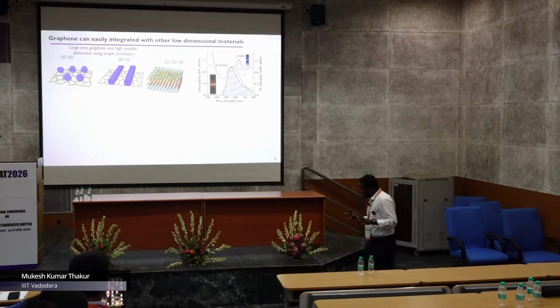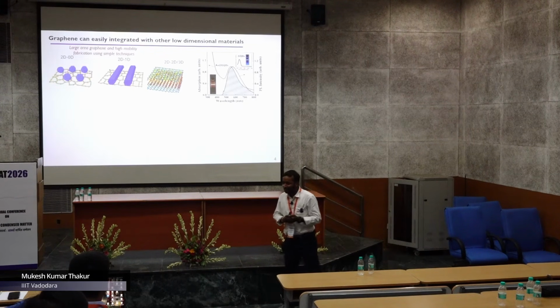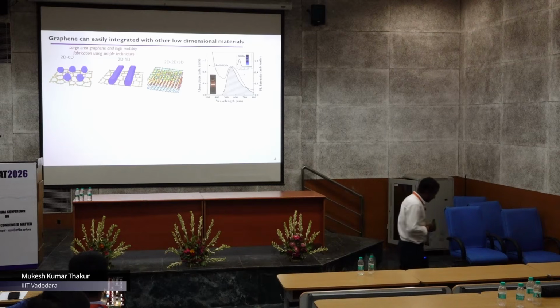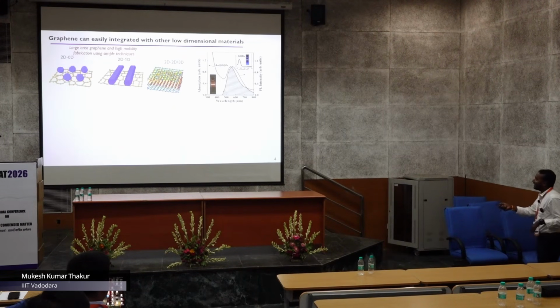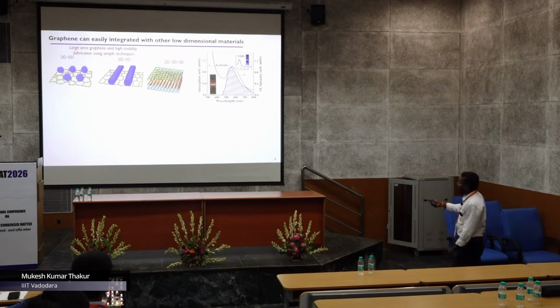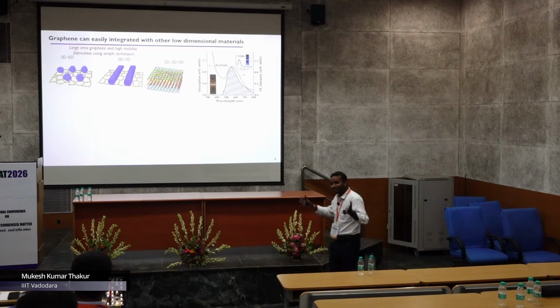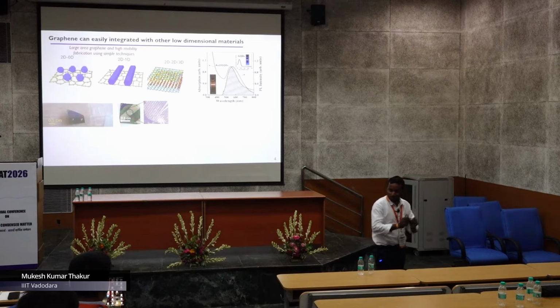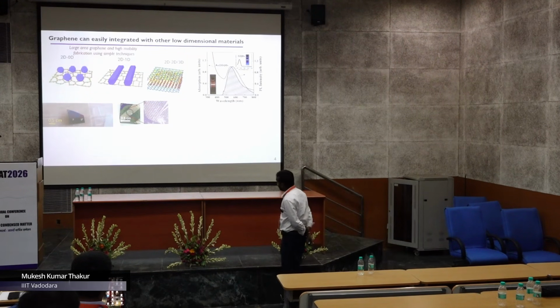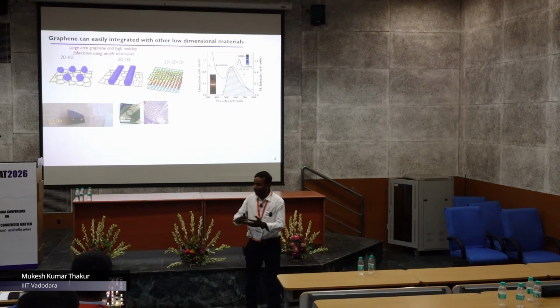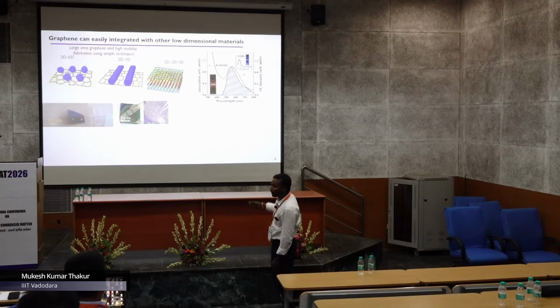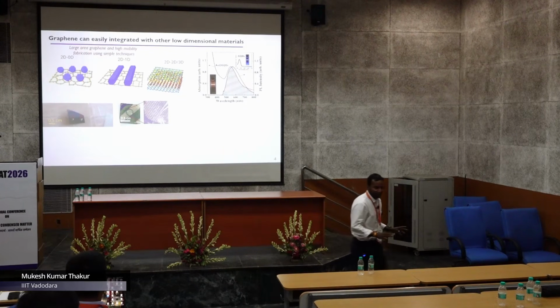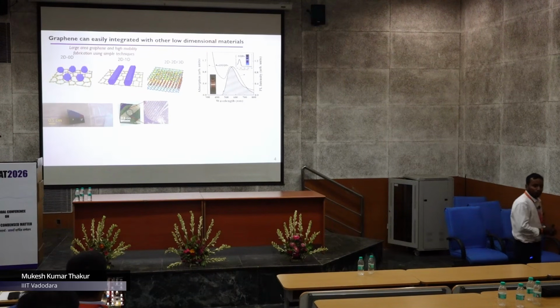So still I stick with graphene. Maybe some people critique why you are still using graphene, it doesn't have a band gap and so on. But it's very easy now to make devices and integrate, right? For example, with a quantum dot. And why I'm saying we don't need a fancy technique like lithography or EBL, simply put the silver paste and put on the graphene and make the contact. The wire, you can simply see a very nice IV characteristic. If you go to micro level, use the TEM grid like the G200, and even with a 0.5 centimeter graphene, you have 200 devices. So there is no need for fancy lithography, and it's very easy to do in the lab also.